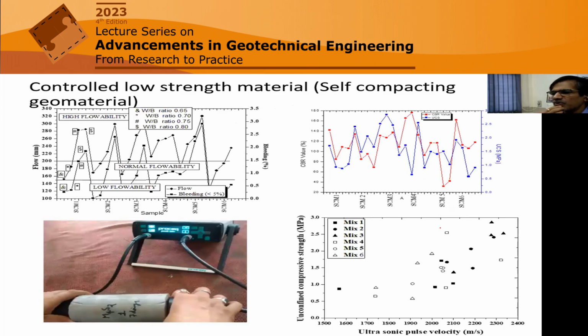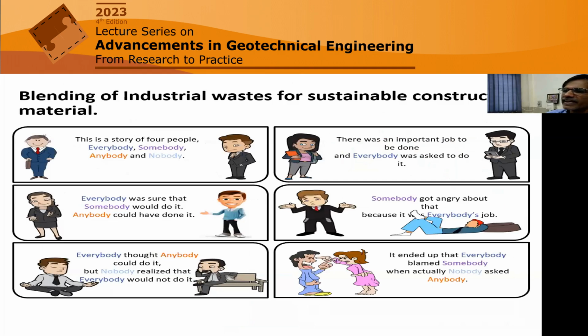So this is one typical study I have shown you on control low strength material, where fly ash could be the major material to increase flowability. And this is possible because the particles are spherical in nature. That's why it is also called a mineral admixture. Spherical particles are not good for geotechnical properties, but they become good for flowability if you are using it for low strength material. So in blending you have to be very careful how much material you are using.